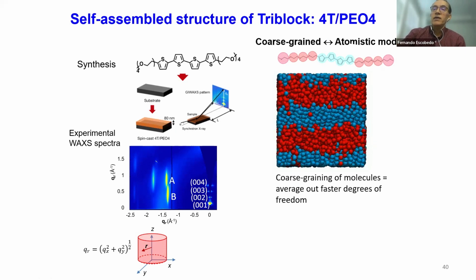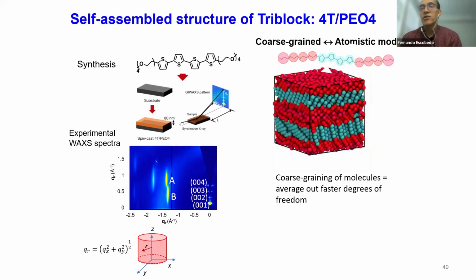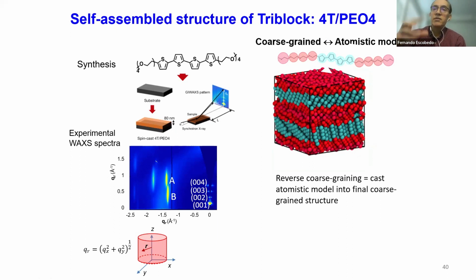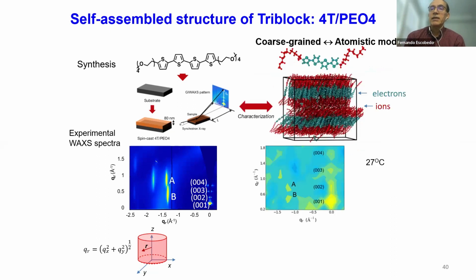And the idea is that once it assembles into the right structure, then we can use that as a template to basically cast the atomistic model into this structure, and then use a simulation, of course, and annealing to fully equilibrate the atomistic system. So that's what we did. That's why we ended up with a structure that looks something like this.